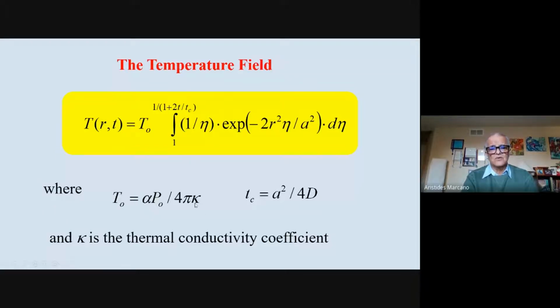Then you have the thermal conductivity K right here. So it just has a regulation for that amplitude. So if you can calculate that amplitude, you can actually get information about the thermal conductivity. But there is also the time evolution of this equation, which is ruled by these coefficients called the time build-up. The time thermal lensing build-up is called TC, which is proportional to the radius of the beam squared and inversely proportional to the diffusivity of the sample. So it means that the time evolution can give you easily the thermal diffusivity of your sample. So this can be used for determination of important thermal characteristics of the sample.